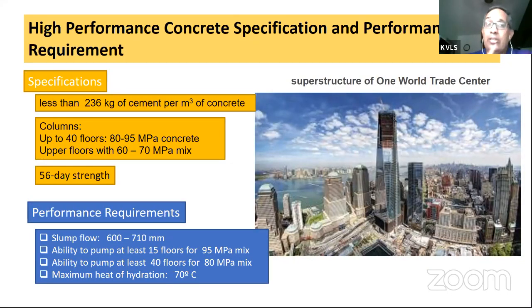cubic meter. Not just that, concrete up to 40 floors had to achieve a compressive strength of 80 to 95 megapascal, and the upper floors had to achieve a compressive strength of 60 to 70 megapascal. So the contractor had to deliver a concrete mix design which achieved a really high strength of 80 to 95 megapascal using a low amount of cement, or a very low weight of cement per cubic meter of concrete.